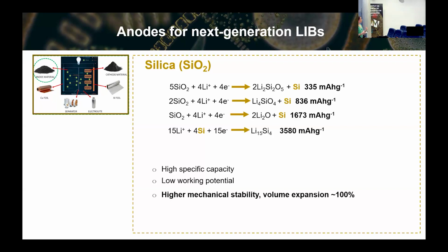So even if we try to use silica as anode material, which has many benefits, like for example, we can use naturally occurring silica sources, and we don't have to do any chemical treatment on it, we still need to nanostructure the material to improve the mechanical stability. So if you see, I talk about all these buffer phases that will consume lithium at some point. So there is a maybe more advanced way of using this principle of having inactive species and active silicon in there.